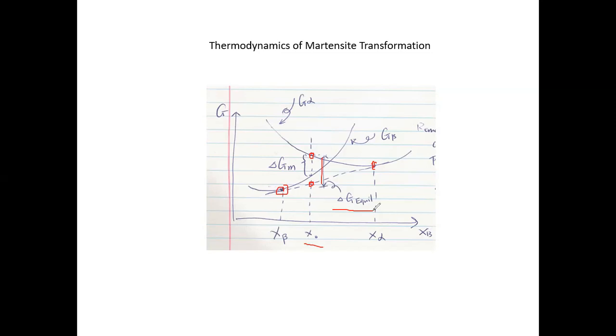Okay, but if this is not possible, if the system is completely stuck in the alpha phase, the free energy will be as high as this. So this is the highest free energy that you can ever imagine at this composition, right? So you have three choices. You can stay as alpha, and the other choice is that you can have the separation, which is the best, but you cannot have that. But don't forget that there's an intermediate choice, which is this. So what does this mean? Well, this means that I cannot completely transform into alpha plus beta, which gives us the best combination and best results in terms of the free energy reduction. But I can always lower my free energy in this particular case by switching from the alpha branch to the beta branch, right? So I start with alpha, but in this case, I can switch from alpha to the beta.